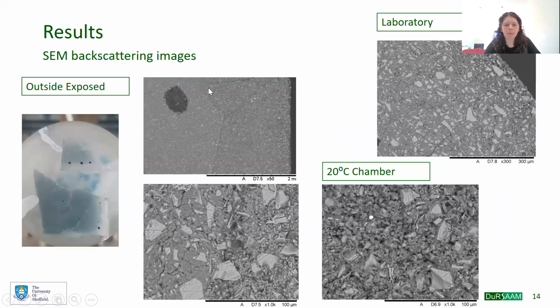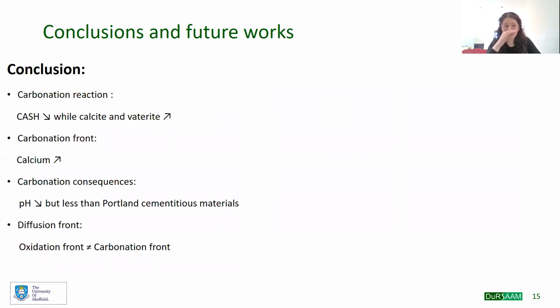For the sample exposed to the rain, the carbonation front is really sharp, but is there. And we can see that even if it's less carbonated in the lab and in this chamber, it's still carbonated, and you can still see the pH dropping. So the conclusions are that the CASH gel lowers during the carbonation, while the calcite and vaterite increase, and that within the carbonation front, the calcium is really high. Also, we can see that the pH is lower when the carbonation happens, but less than for Portland cementitious materials, which is really good because it might not be an issue for the steel reinforcement.